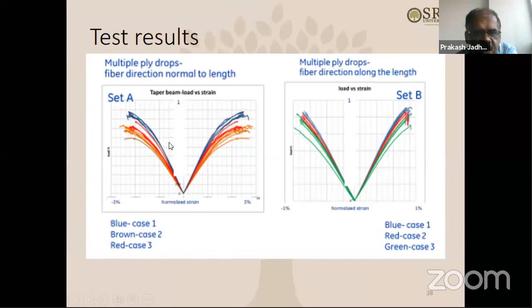Of course, one set of the cases was fiber direction normal to the length. The other set of the cases was fiber direction along the length. And then we saw case one, case two, case three. Case one is of course a baseline case because the ply drop location is at the middle thickness, so it's not going to affect performance. So of course, case two and case three should show different results. And that's what happened here. You can see the load versus strain plots, where case two and case three, brown and red, are showing different results compared to case one. Also in set B, where fiber direction was along the length, case two and case three are showing results at different, better load levels.